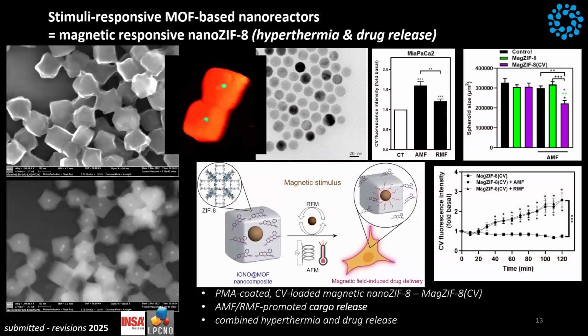And what we demonstrated also here is that the particle is the seed. By controlling the number of seeds, you control the final concentration of particles. If you put a lot of these seeds, you will end up with a lot of nanoparticles, because in each seed, you grow the MOF. If you put few of them, you will make a thicker shell. Okay? So we have demonstrated also with alternating magnetic fields and rotating magnetic fields. And we are also able to destroy tumors and release a drug.